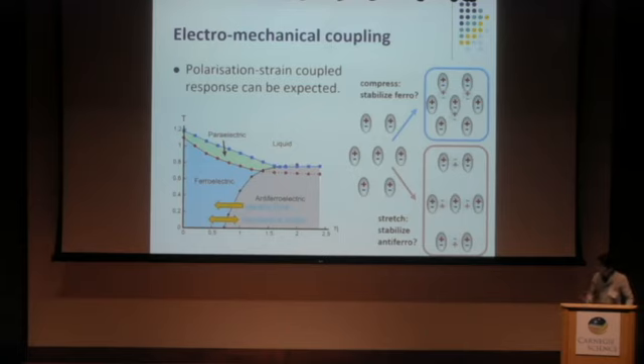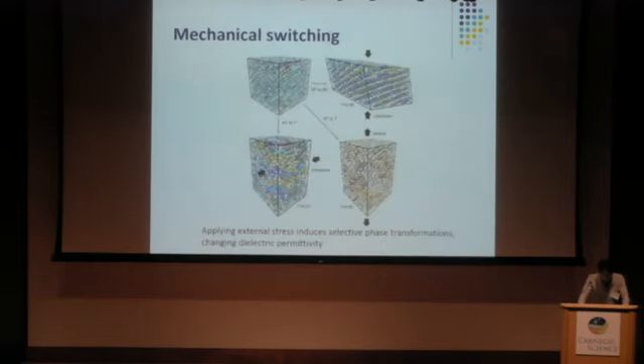Since in our model a strong electromechanical coupling exists, we can expect that the ferroelectric phase and antiferroelectric phase can be controlled by external stress. This is a schematic picture. Suppose we have the ferroelectric phase and stretch in this direction; the relative position of the dipoles changes, and for this stretching case, the antiferroelectric phase will emerge. So this is one example of mechanical switching.